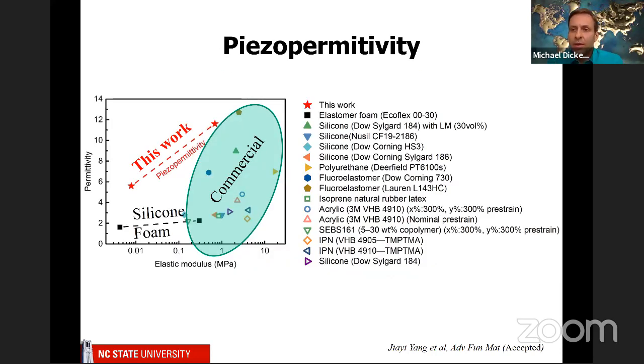The other kind of neat thing is because we use foams, we're able to make really soft material. So this is the elastic modulus of every kind of silicone we could easily find online. And you can see that most of the commercial elastomers fall in this range. If you take one of those and make it into a foam, you get it to be much softer, which is intuitive. However, the dielectric permittivity is quite low. So the cool thing here is we can have really soft material, but have a large change in permittivity.